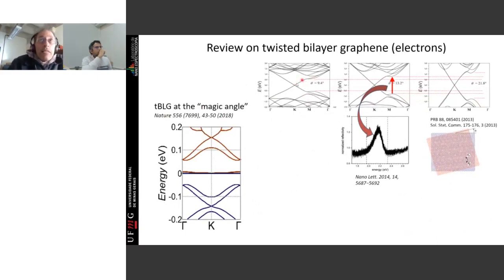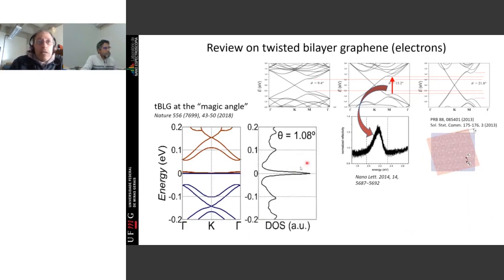Then the electronic structure generates a flat band right in the Fermi level, right in the energy where you divide the conduction band and the valence band. And this generates a high density of states here, which is demonstrated here, okay? You have a lot of states at this energy, and it was observed that in this situation graphene becomes a superconductor. Okay. So notice that just by rotating one layer with respect to the other, you are completely changing all the electronic, phononic, and all the properties of these materials.